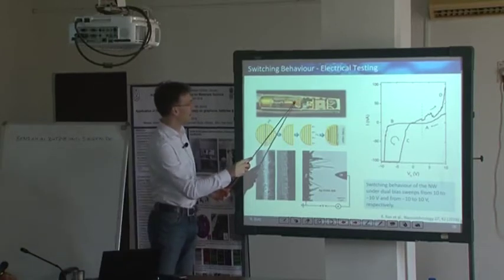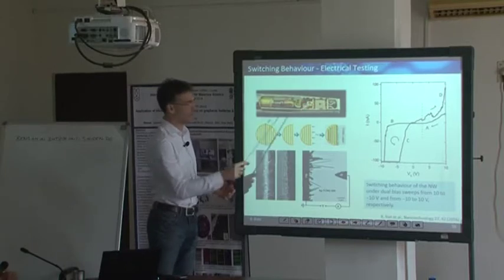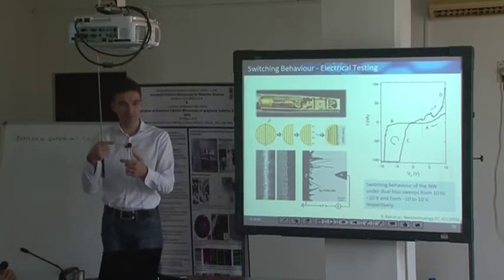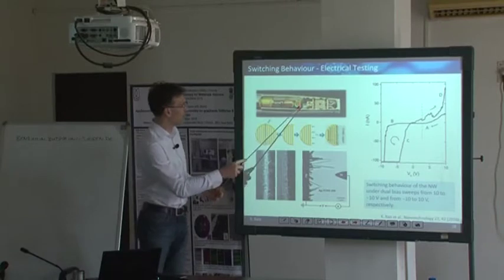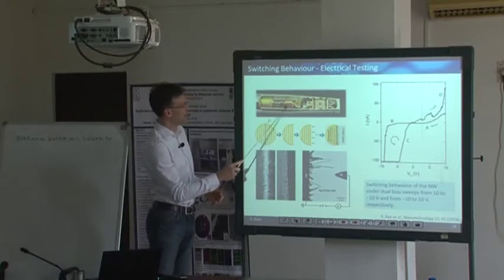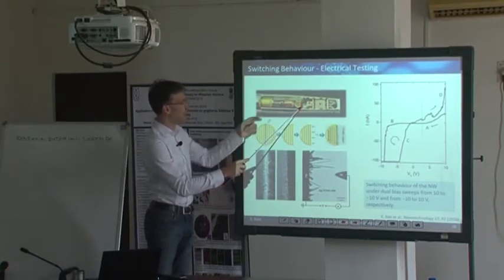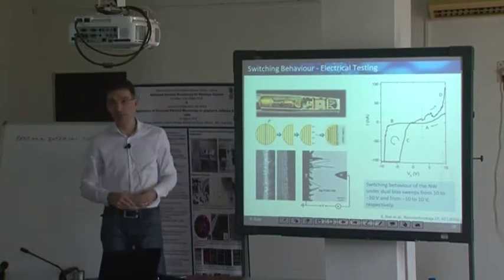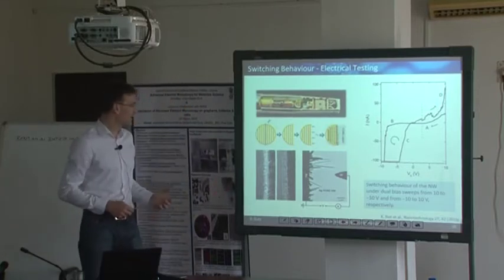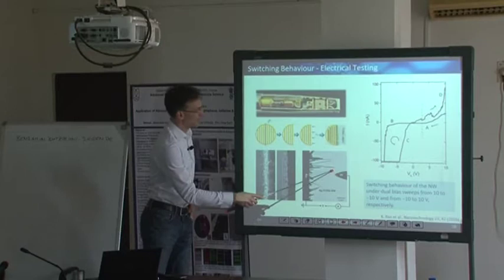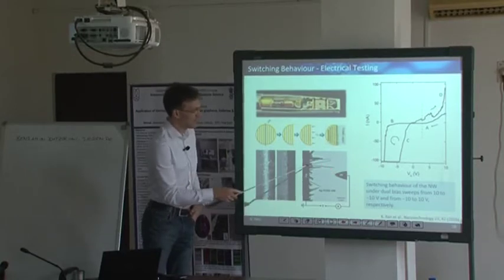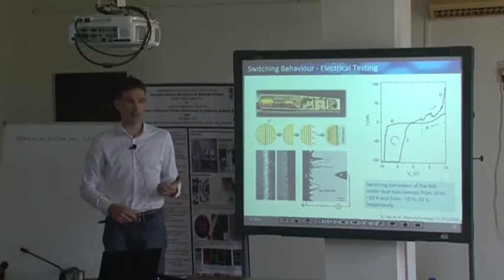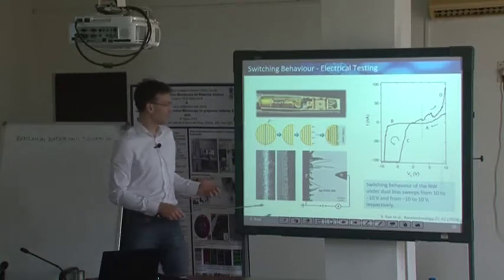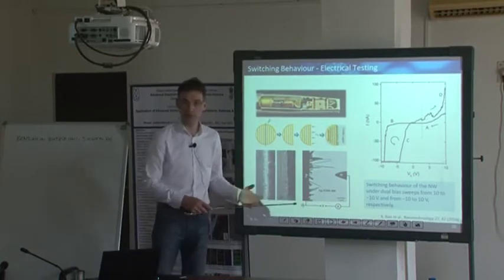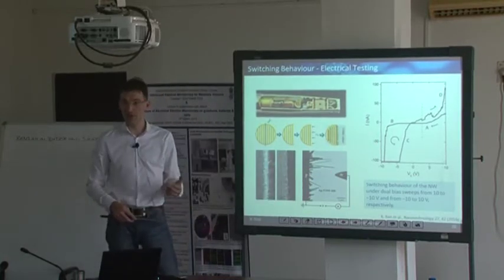So in this particular case, the TEM sample is mounted on the left-hand side, and on the right-hand side you have a metal tip installed, and you can manipulate your sample and move your sample and contact very, very locally. This is one example where we measured the switching of TCNQ nanowires, so this is more of an organic molecule, and by introducing currents up to a certain field strength, you will see that the resistivity changes.